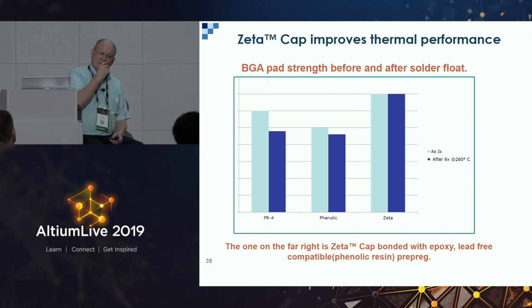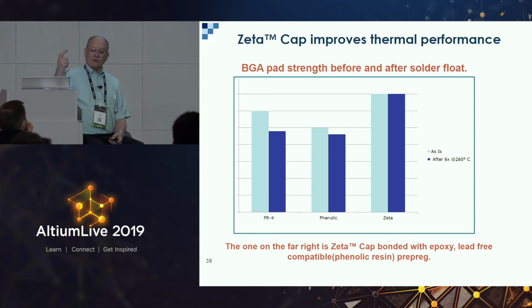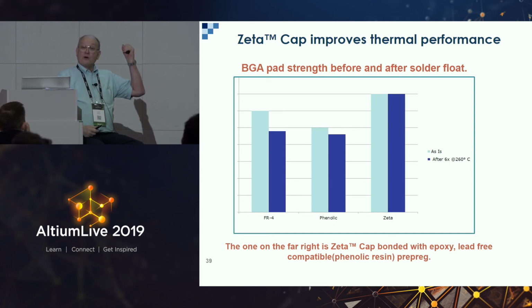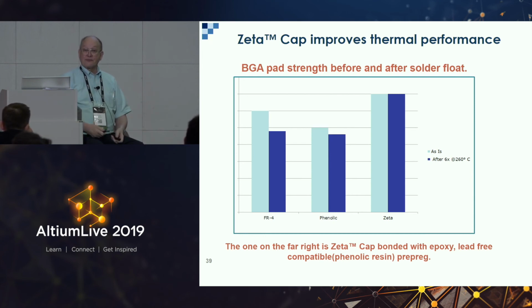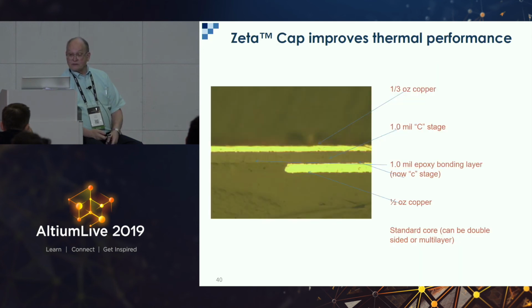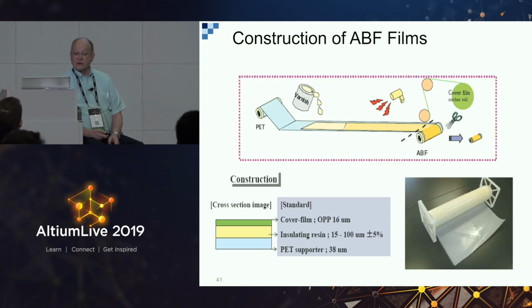When we had tin lead, we had dicy-based systems that were kind of rubbery, which was great. When we had to go to higher reflow temperatures, we had to go to a higher temperature thermoset, which is pretty rigid, and that's what we call cracking. Well, one of the solutions is this material where the copper is attached to a polyimide layer that has a higher temperature resistance than the epoxy layer. So Zeta Cap improves thermal performance for fine pitch BGAs, especially if you're encountering cracking in your board design.